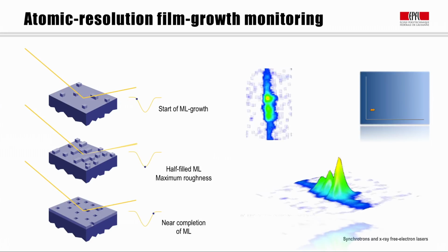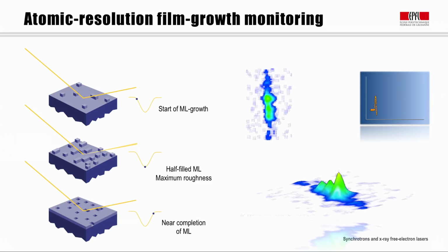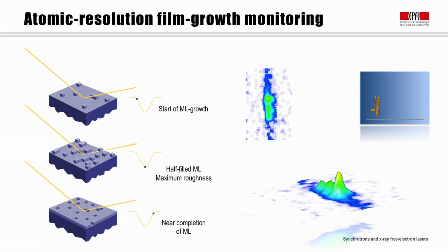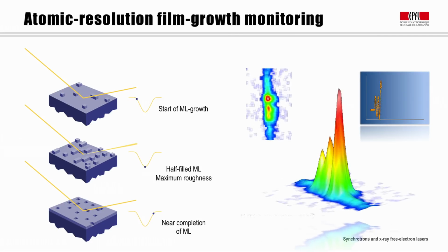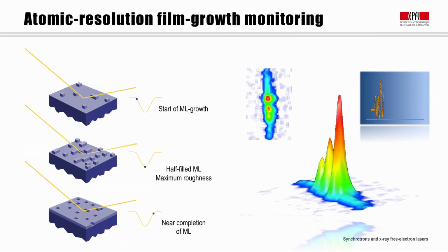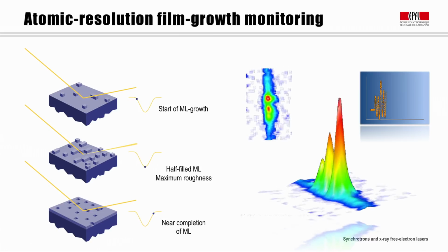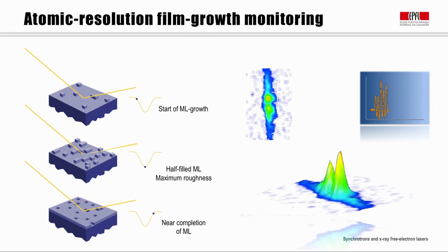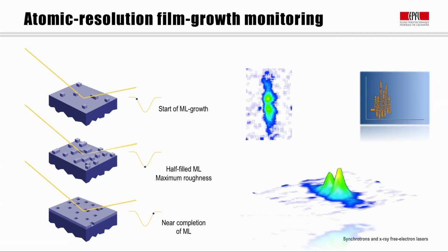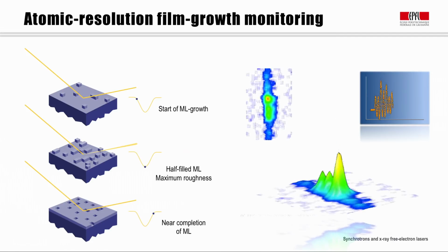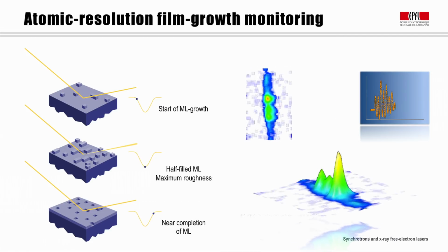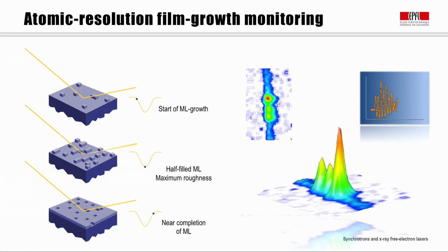The movie of the growth in real time is shown here as an example. Note first that the intensity initially increases at the start of growth, which is indicative that the substrate material on which the film grew was not perfectly atomically flat to begin with, and that the first part of the growth filled in this incomplete monolayer.